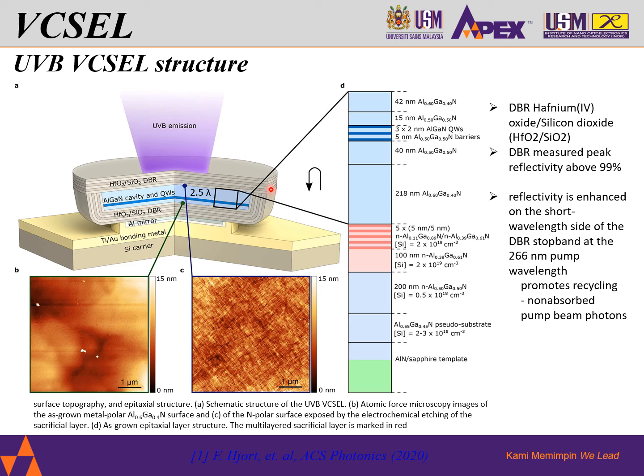The top DBR is a 10 pair DBR, has a stop band centered at 320 nanometer and measured peak reflectivity above 99%. The bottom reflector ends with an additional DBR pair and aluminum mirror. The reflectivity of the DBR is enhanced at the emission wavelength through this structure. Even more importantly, the reflectivity is also enhanced in the short wavelength side of this DBR stop band at 266 nanometer pump wavelength, which promotes recycling of the non-absorbed pump beam photons.